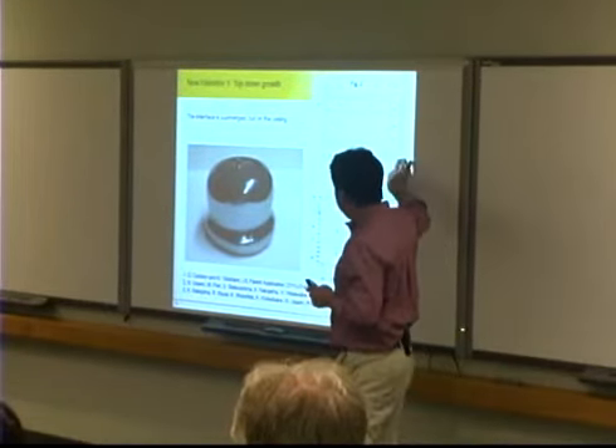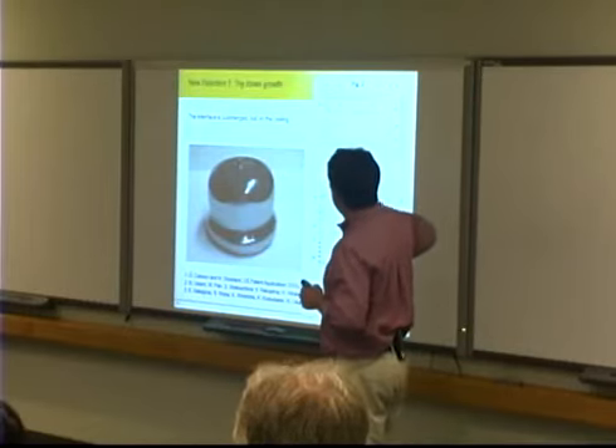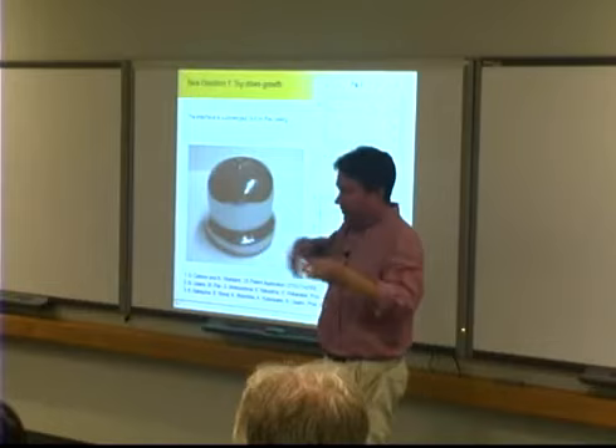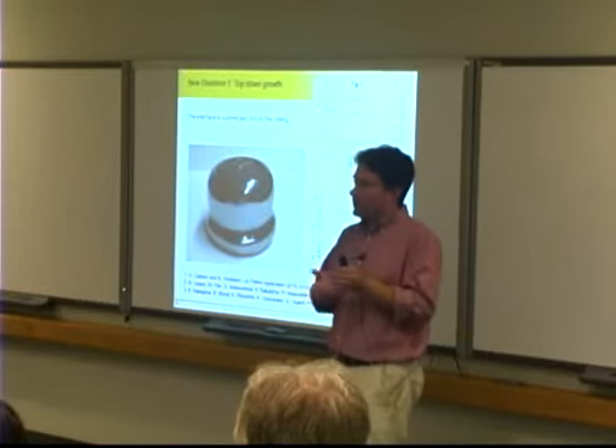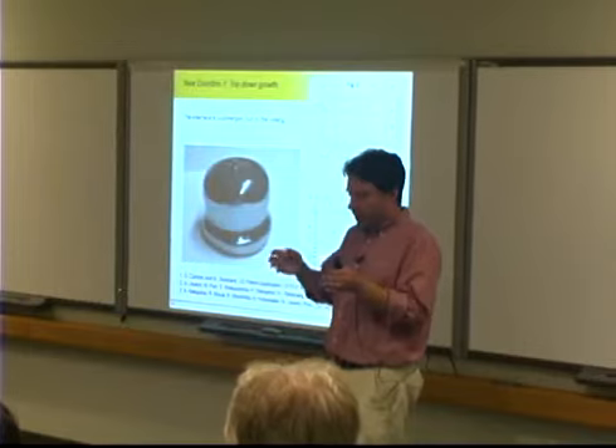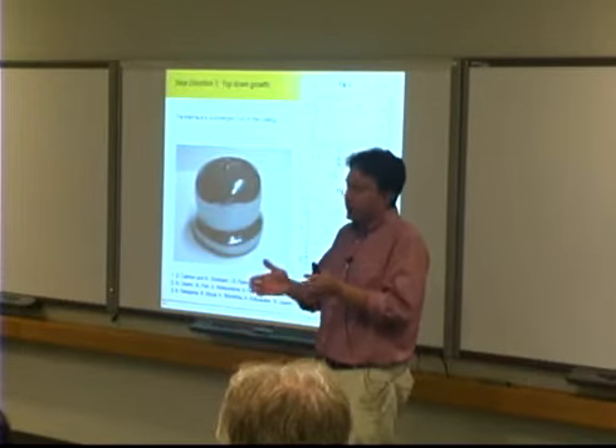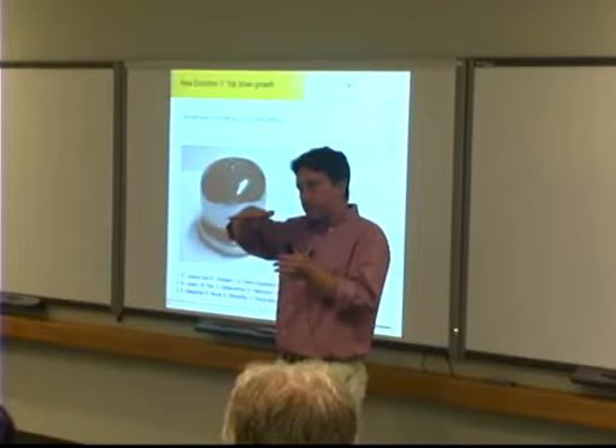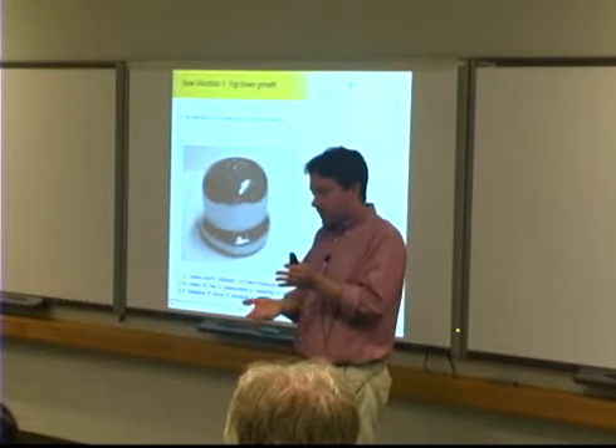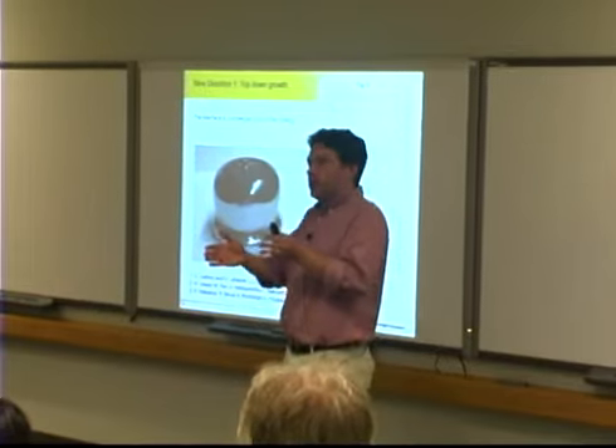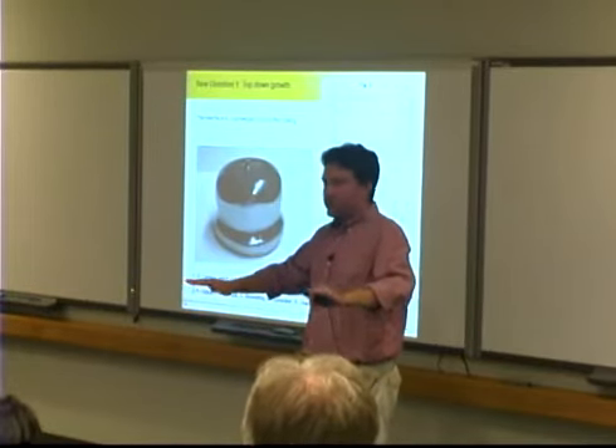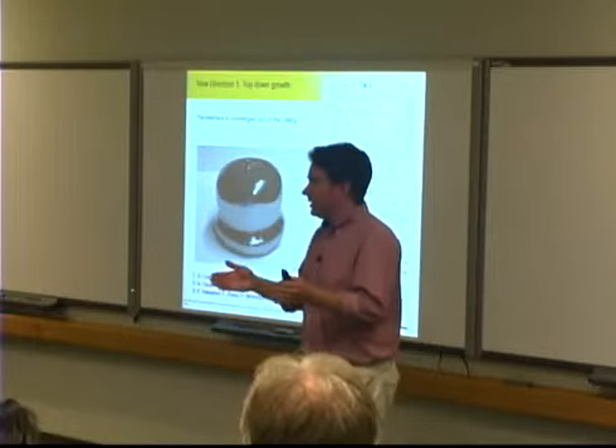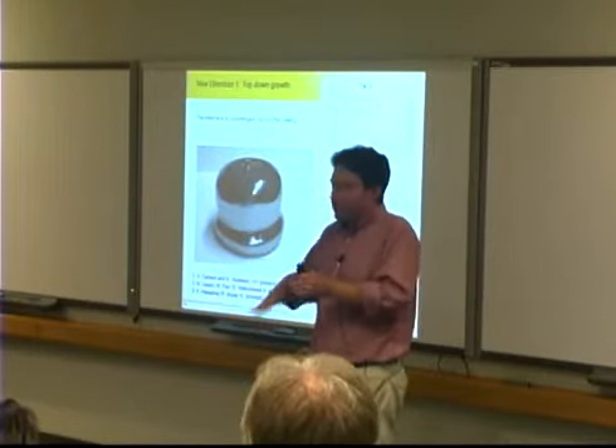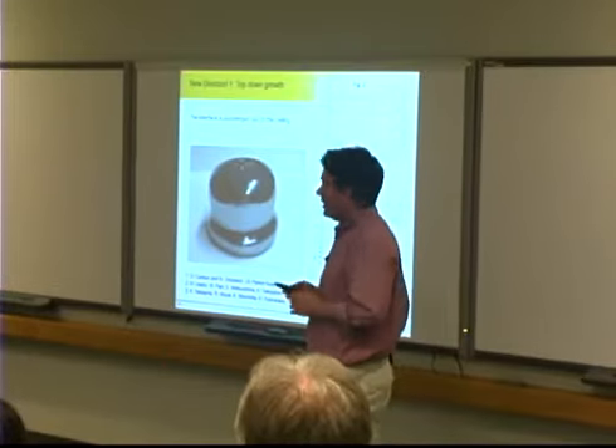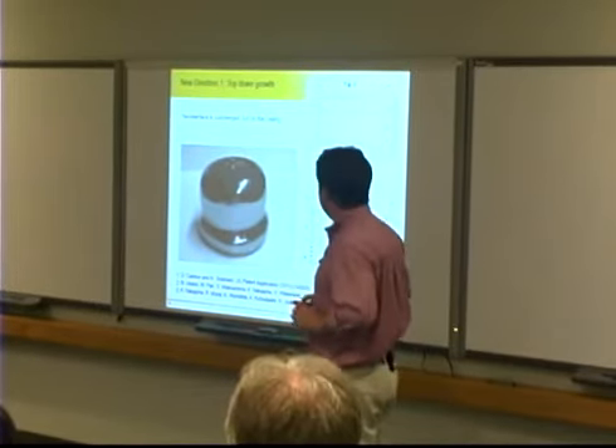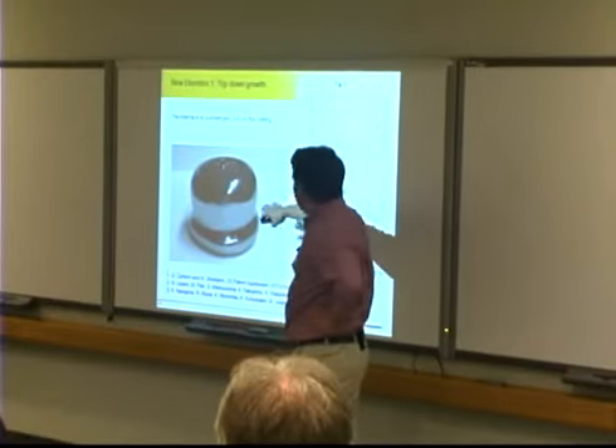But a group in Japan has picked up on this, and they've done something very clever. They've essentially set a four-wall bottomless crucible inside a larger crucible, and they've managed to get the silicon not to leak out of that bottom seal. They start top seeding and grow it down, and as the pressure gets high enough, it simply raises the wall enough for the liquid to squirt out, then it sets itself back down and reseals, and they continue growing. They end up burping silicon at the bottom a couple of times. But it's actually kind of clever, and the silicon pressure never gets too high.